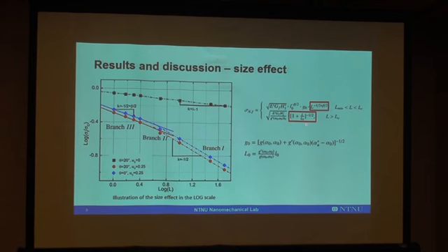That means when the grain size is far larger than L0, we have the branch 1 size dependence. If it's comparable to L0, then we have the transitional region. And when the grain size is smaller than the critical value, the development of the failure process zone is confined. So we have another form of size effect, which corresponds to branch 3.